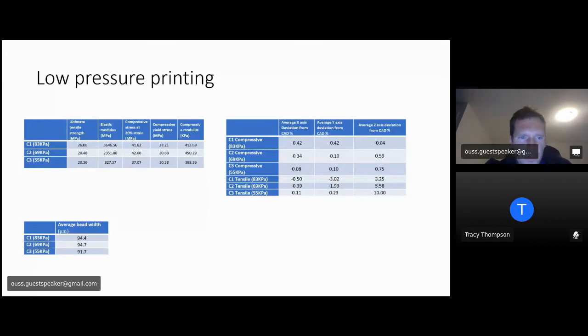So printing at a lower pressure, as you can see, the ultimate tensile strength is the lowest at 55 kPa. The elastic modulus is the lowest. Compressive stress test at 20% strain is again the lowest. And the compressive yield stress in megapascals, that is again the lowest. And compressive modulus, again, the lowest. So there's some really strong evidence there that actually 3D printing parts at a lower pressure reduces the mechanical strength of your parts. And then again, you've got your deviation from CAD and your bead width.